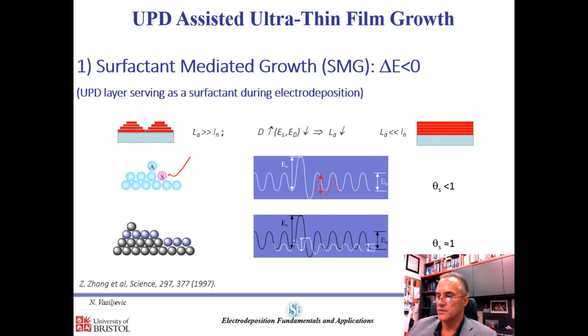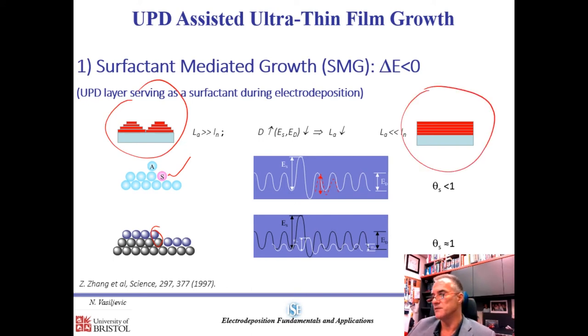Or if they're really in a full coverage regime, then they mitigate the step barrier and also mitigate the diffusion process on the terraces. And with respect to that, we can actually make a system that goes typically 3D, grow 2D, because we significantly reduce the length scale related to the step-down processes I discussed before, L sub alpha.